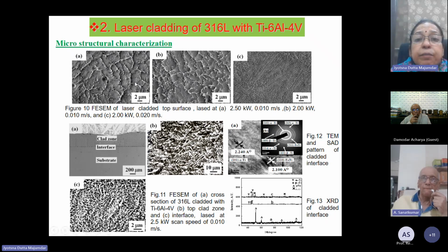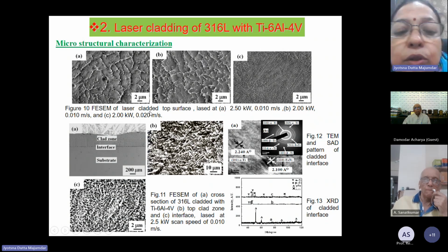So this is the typical top surface of laser surface clad 316L stainless steel with Ti6Al4V. We find that on the surface there was a typical alpha-beta structure. There are no flaws or defects on the surface. It is perfectly flaw free. And at the interface, if you see carefully, there is minimum dilution. There is no dilution at the interface, and also no defects, it is quite crack free and defect free.